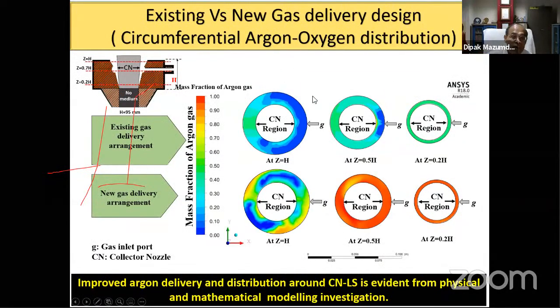is shown here, that you have two different cases, the existing design, and whether we go here at the lower part, at the intermediate part, or at the top part, the existing design shows that nowhere is there a red region, nowhere is there even a little bit of argon, most of it is air. On the other hand, the new design shows us that at the bottom part it is going to be red, or argon, at the intermediate part is also going to be red, and somewhere at the top, we can have about 90–95% of argon present there.